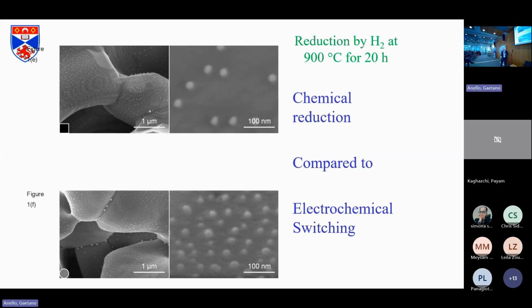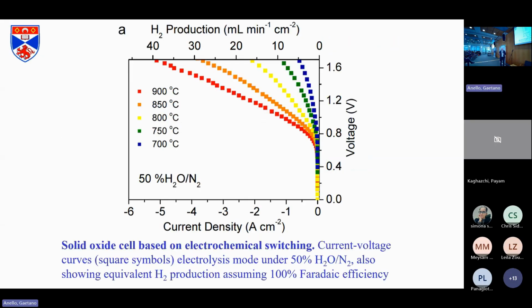So the reduction took overnight at 900. The switching is in 50% steam, 50% nitrogen. That just took a couple of minutes. So electrochemistry is very powerful. Applying 2 volts is quite significant. So you can redrive these processes. And then that worked really well for steam hydrogen production. Getting 3 amps per square centimeter is pretty much state of the art for solid oxides. And what the company people would have said was impossible, it's very pleasing after a number of years to show that we can actually make new materials that work.